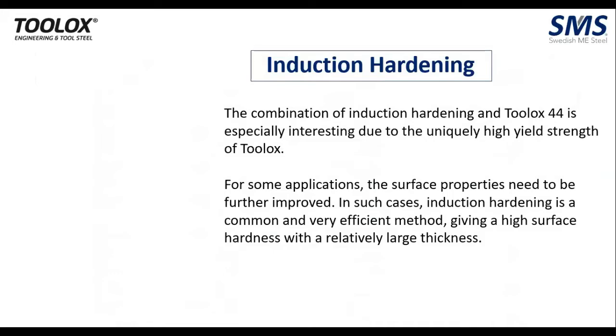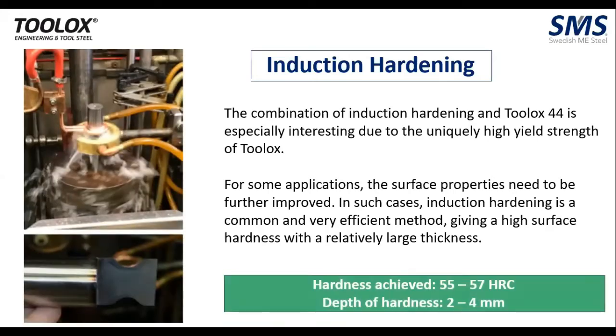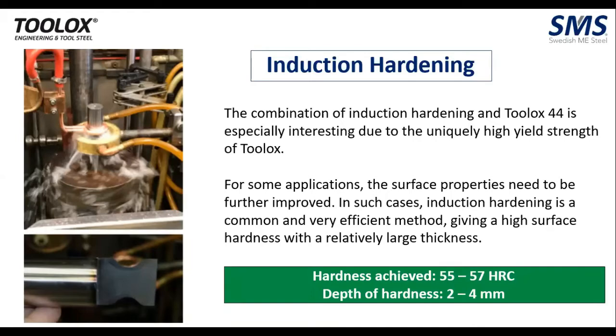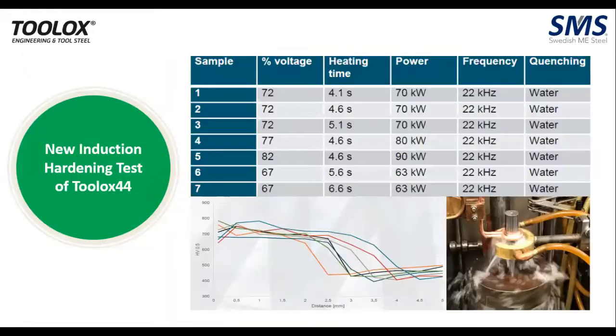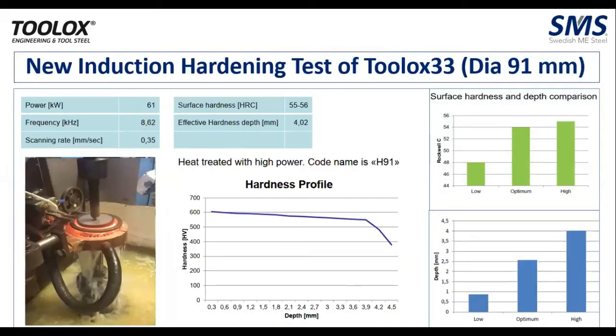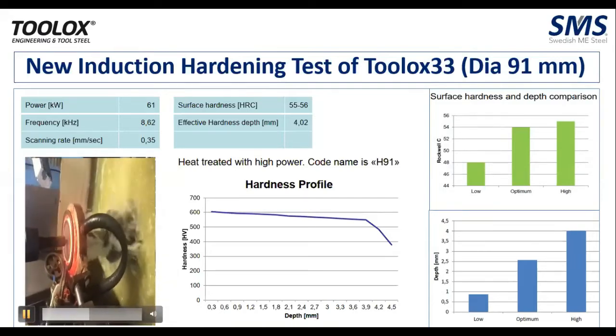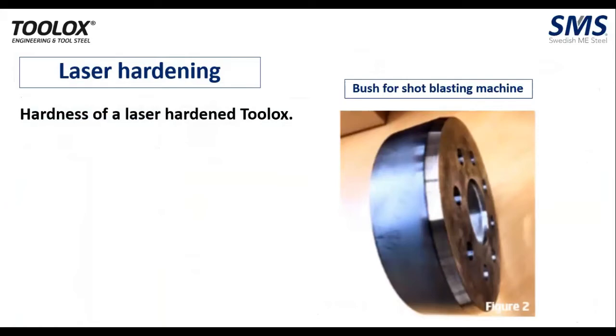Since the yield strength of the metal is very high, the combination of Toolox 44 and induction hardening is very unique. It can be used in various applications wherein wear resistance is very much required with different types of plastics. So induction hardening can be one option. Hardness achieved is 55 to 57 HRC with a hardness depth of 2 to 4 mm. We have done the procedures for induction hardening on Toolox 44, and even on the Toolox 33 grade. This is a small video for that. It's a bush, a component used in a shot blasting machine.